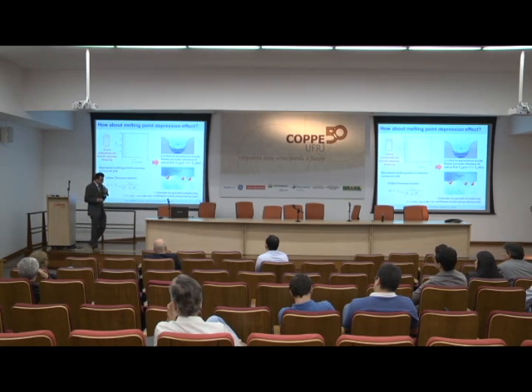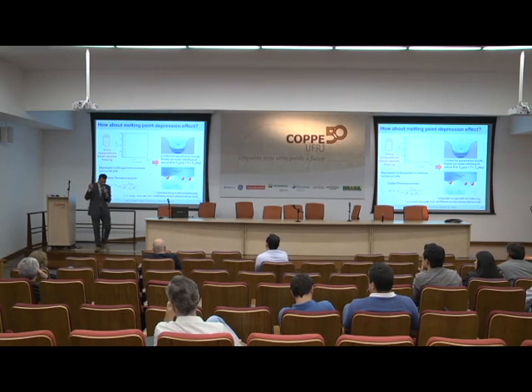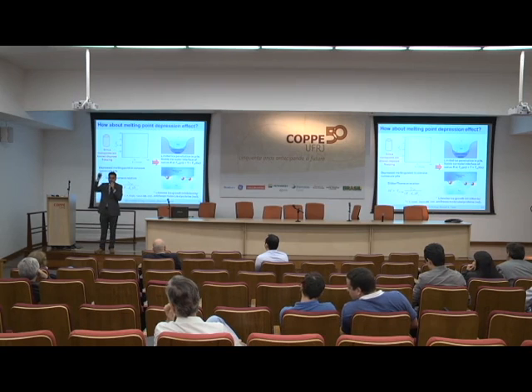Well, we can borrow something from basic thermodynamics, which atmospheric science people know very well, actually. And that has to do with the so-called Gibbs-Thomson relationship, which tells you that if you have water in a small pore, a silica nanopore, for instance, a few nanometers in diameter, the freezing point will be depressed. It has to do with the simple fact that the ice nuclei are not able to form due to the confinement of the pore. Okay? That's a very simple way of putting it, but that's essentially at the heart of it.